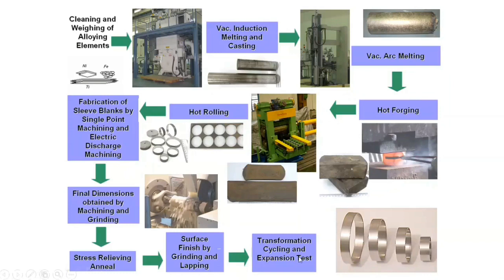It's very easy to roll, and by a combination of single point machining and also grinding, and of course we cut it out by EDM, we can take out the final sleeve and do some transformation cycling, and we do some tests. This transformation cycling is trying to impart some kind of memory to it. We do that to get the final sleeve.